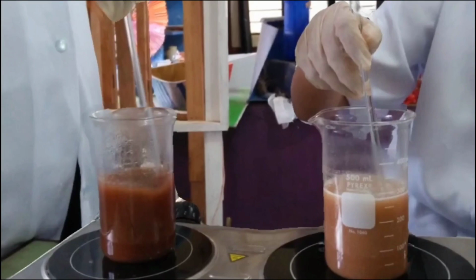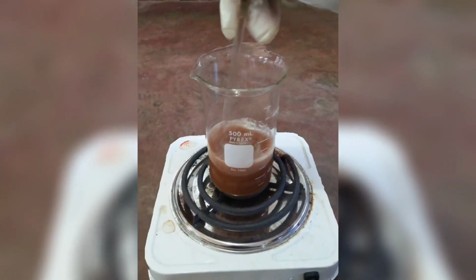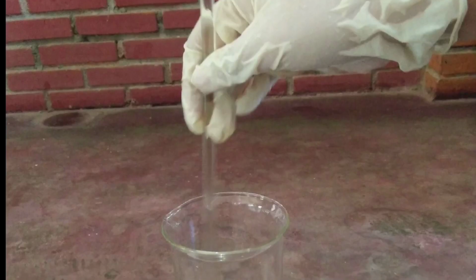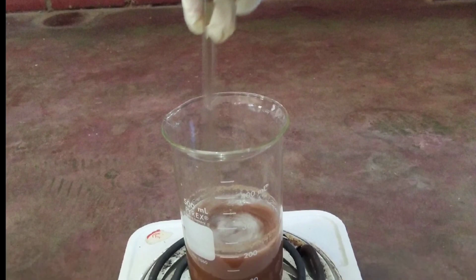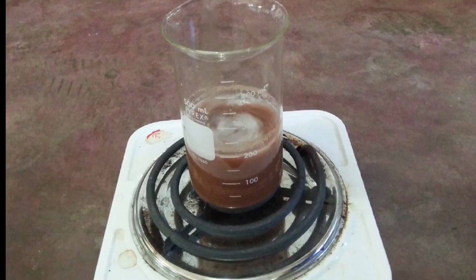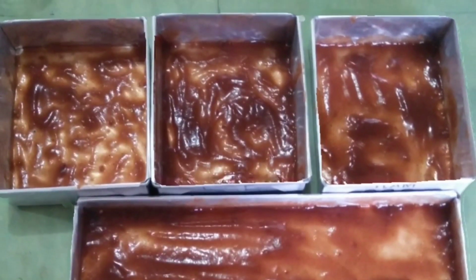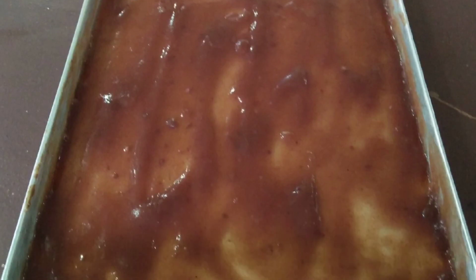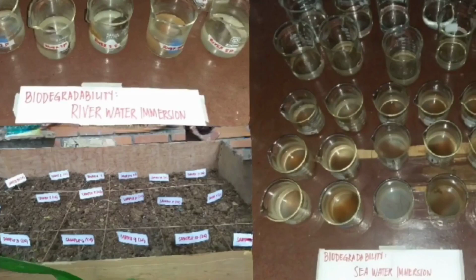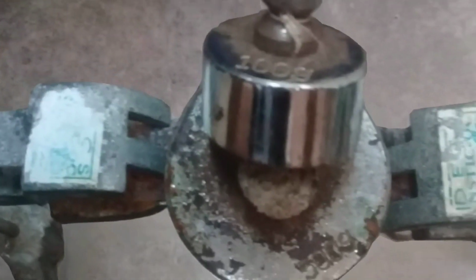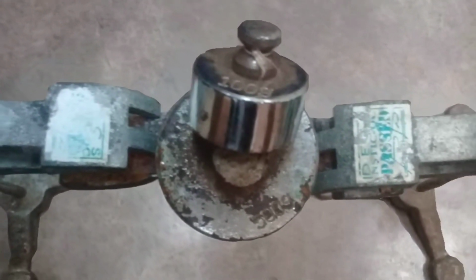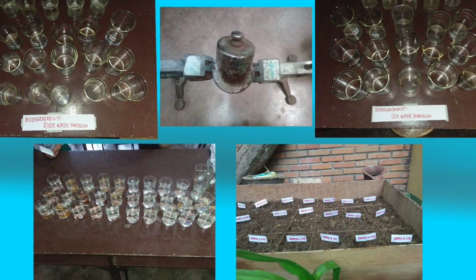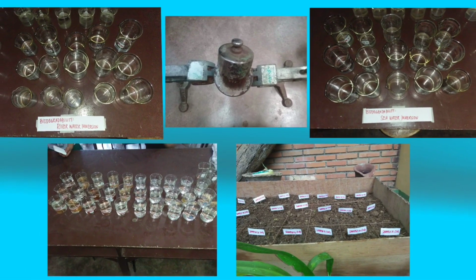8 ml of glycerol was added as plasticizer and stirred. It was cooked under low fire on an electric stove, stirred constantly until the mixture turned into an opaque gel with a brown color. It was spread on a 6x5 inch molder and sun-dried for a day. The sheets were cut into 1x2 inch to use for water uptake and biodegradability test, and 1x3 inch for tensile strength. 15 replicates were used for each parameter for a total of 80 replicates.